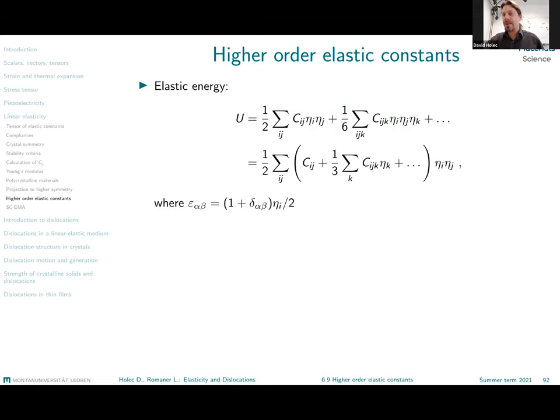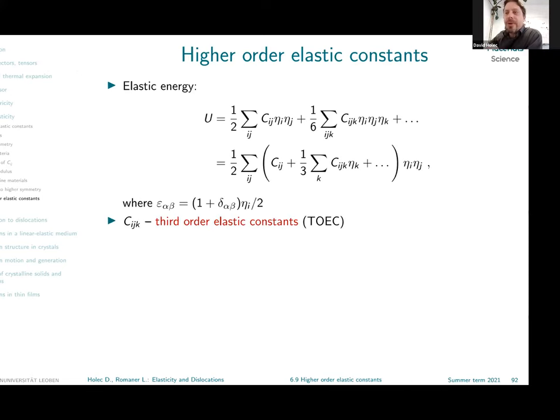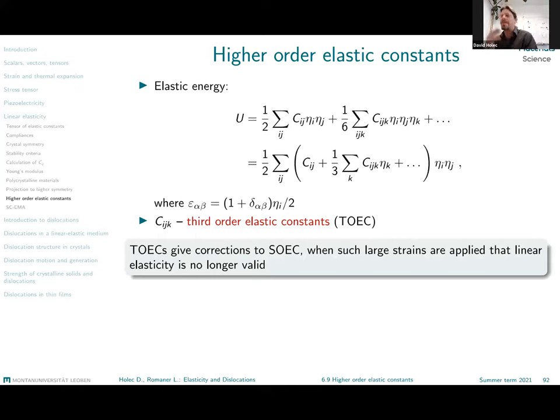You can rewrite this easily also in such a form that actually if we stop the expansion here after the third term, then we end up with a correction of the second order elastic constants with applied strain. That means that applying strain leads to stiffening or softening of the elastic constants. They are not constant, but the constants are really stress or strain dependent. And this is what is expressed in the first place by this third order elastic constant, sometimes also provided in the literature. And they essentially provide the corrections to the second order elastic constants for reaching out of the linear elasticity